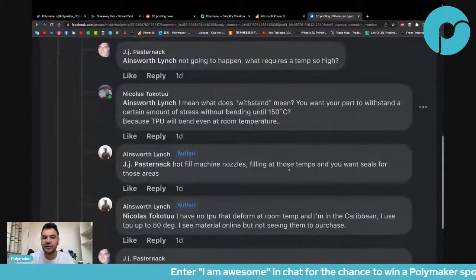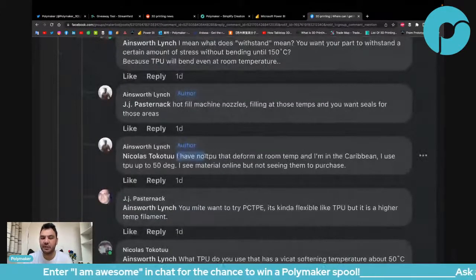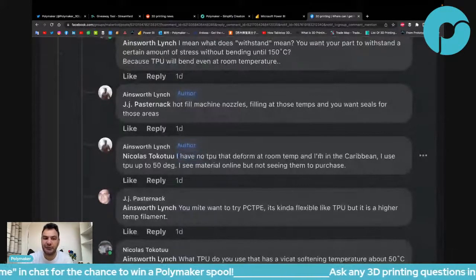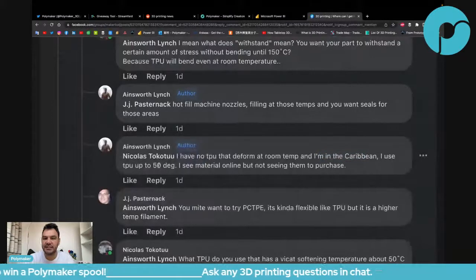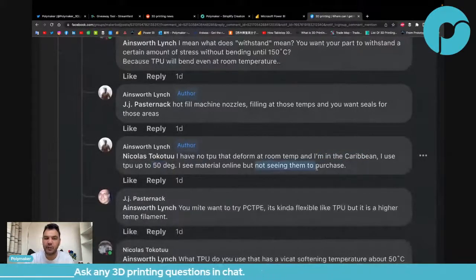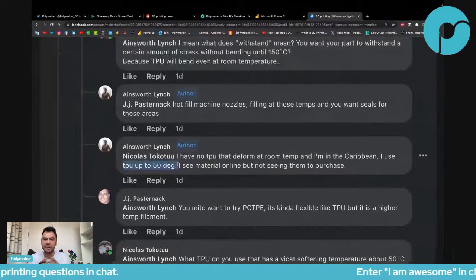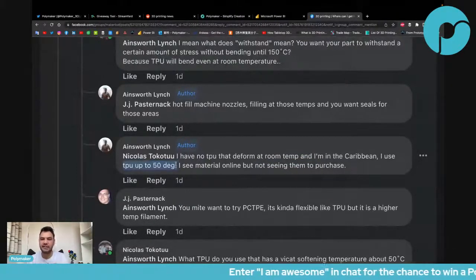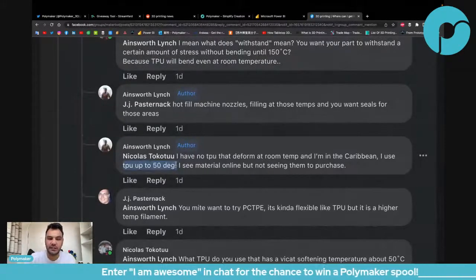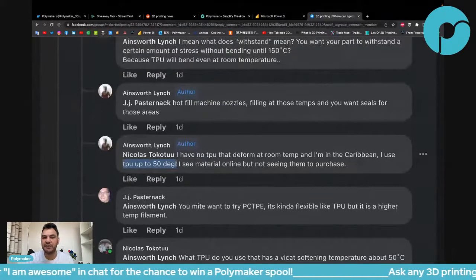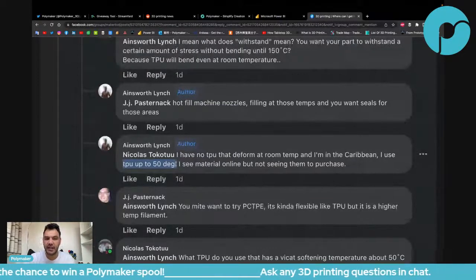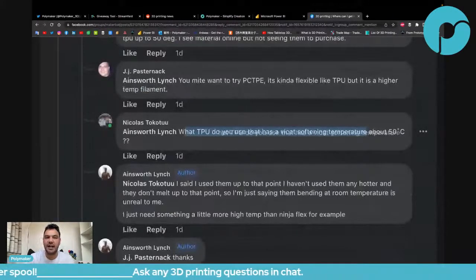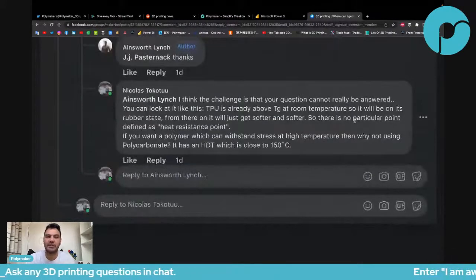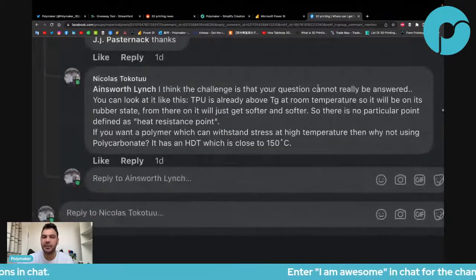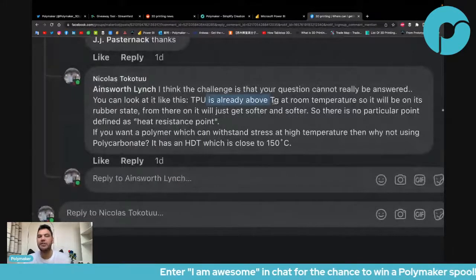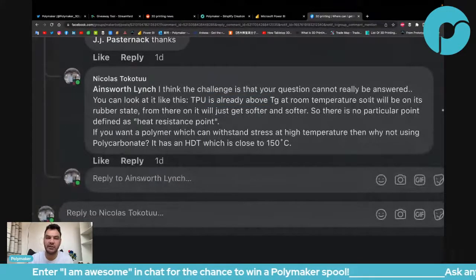Then he said, I have no TPU that deforms at room temperature. I'm in the Caribbean. I use TPU up to 50 degrees. I see materials online, but not seeing them to purchase. So he's using TPU up to 50 degrees. What does that mean? Does that mean TPU is completely rigid, and then at 50 degrees suddenly it's flexible? And then I asked, what TPU do you use that has a Vicat softening temperature above 50 degrees? And then I explained, I think the challenge is that your question cannot really be answered. You can look at it like this: TPU is already above Tg at room temperature. The Tg of a regular TPU is maybe around -20, -30 degrees, right?